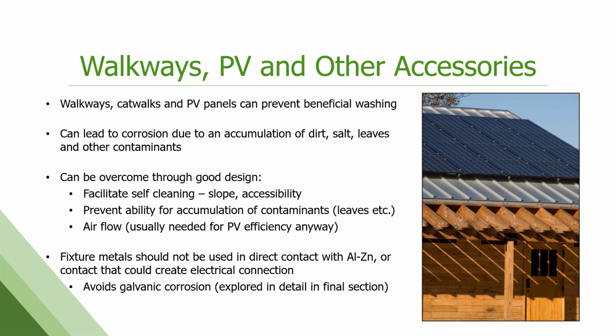And of course, airflow for solar panels is really needed anyway. You want to make sure you have enough of a gap between the roof and the panels that nothing's getting stuck and being held behind those panels. Fixture metals should not be used in direct contact. We're going to talk about galvanic corrosion in the final section, but you have to be careful about dissimilar metals. Copper is especially problematic with coated steel. You see copper and runoff from copper sometimes on solar installations and HVAC equipment, and it ends up causing premature corrosion.